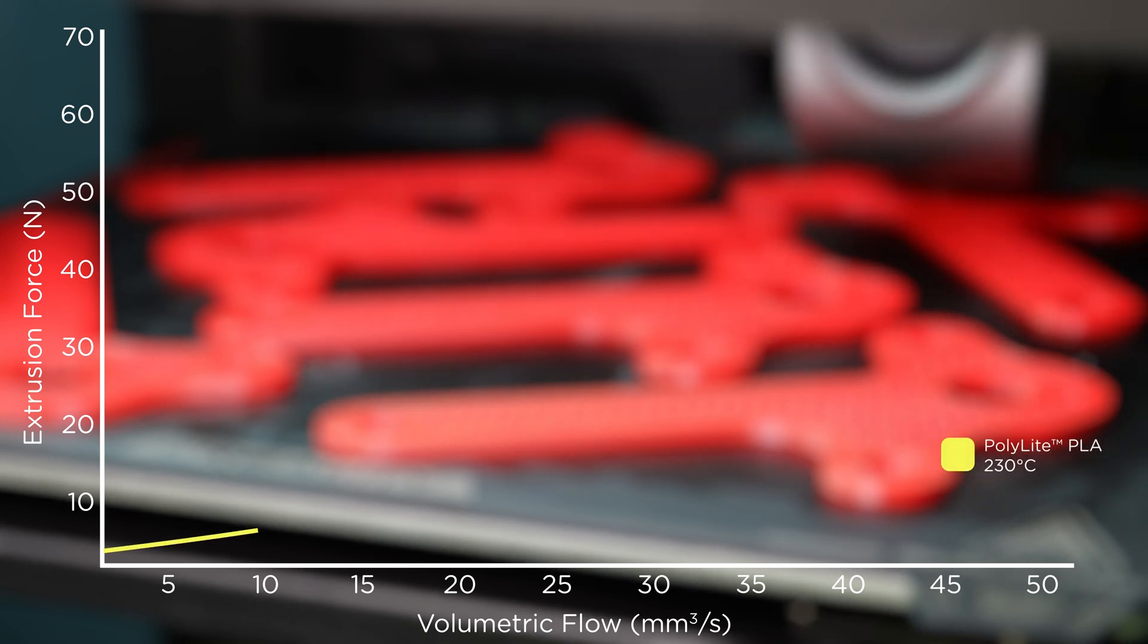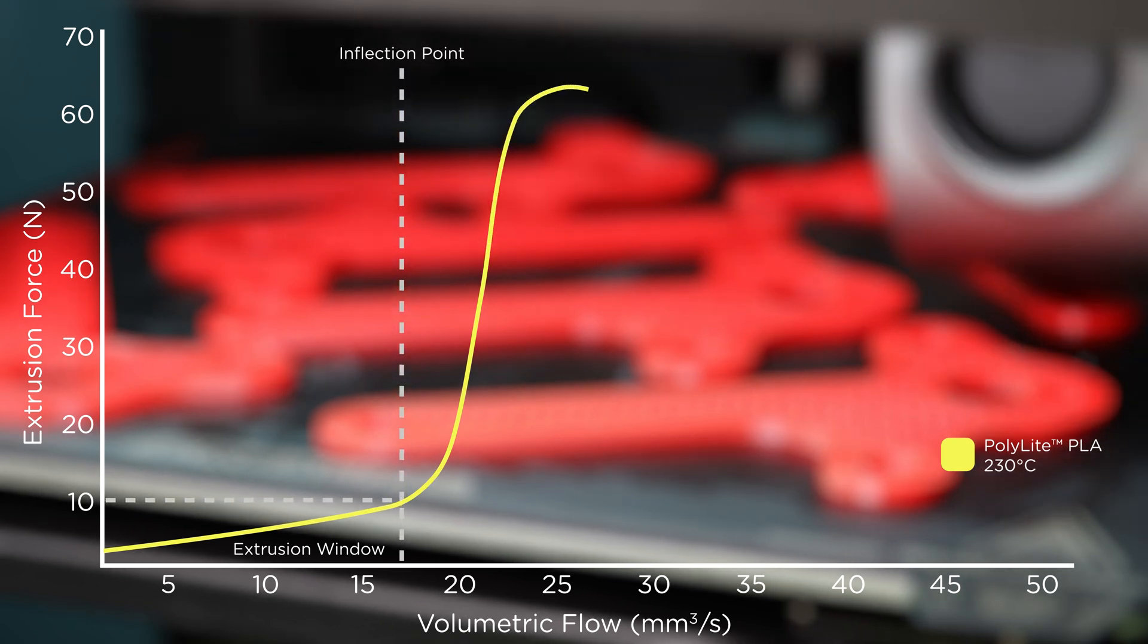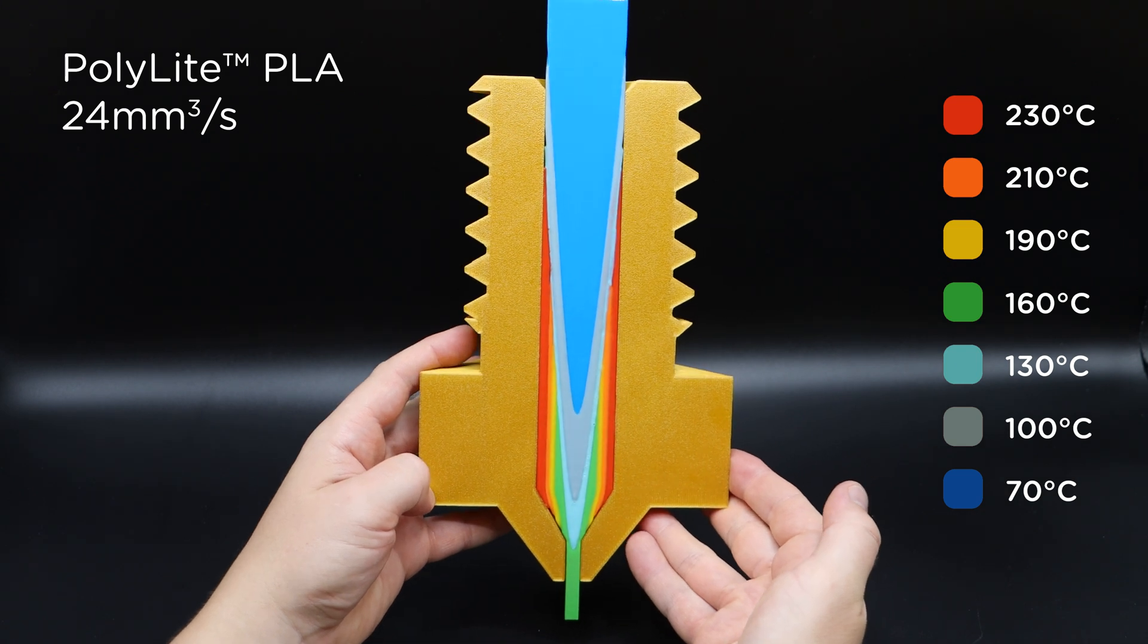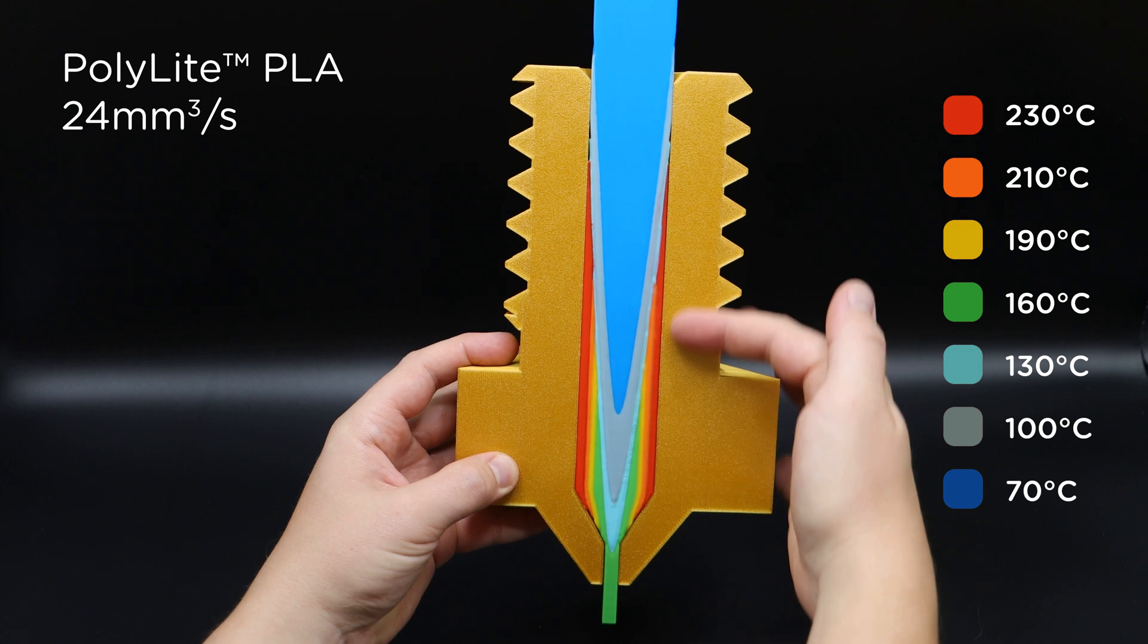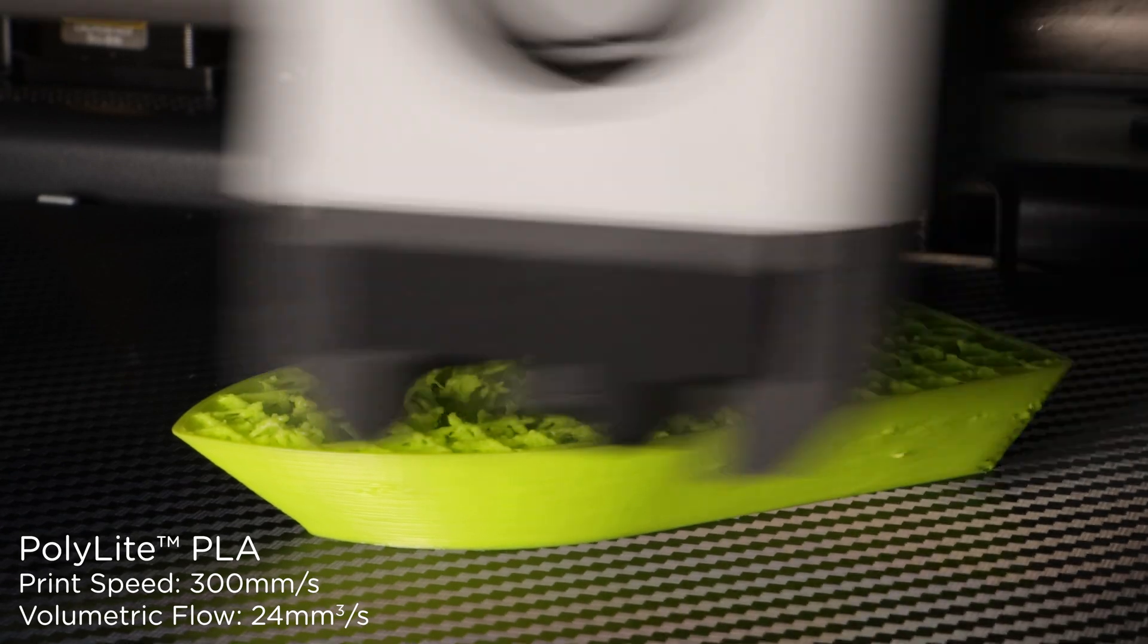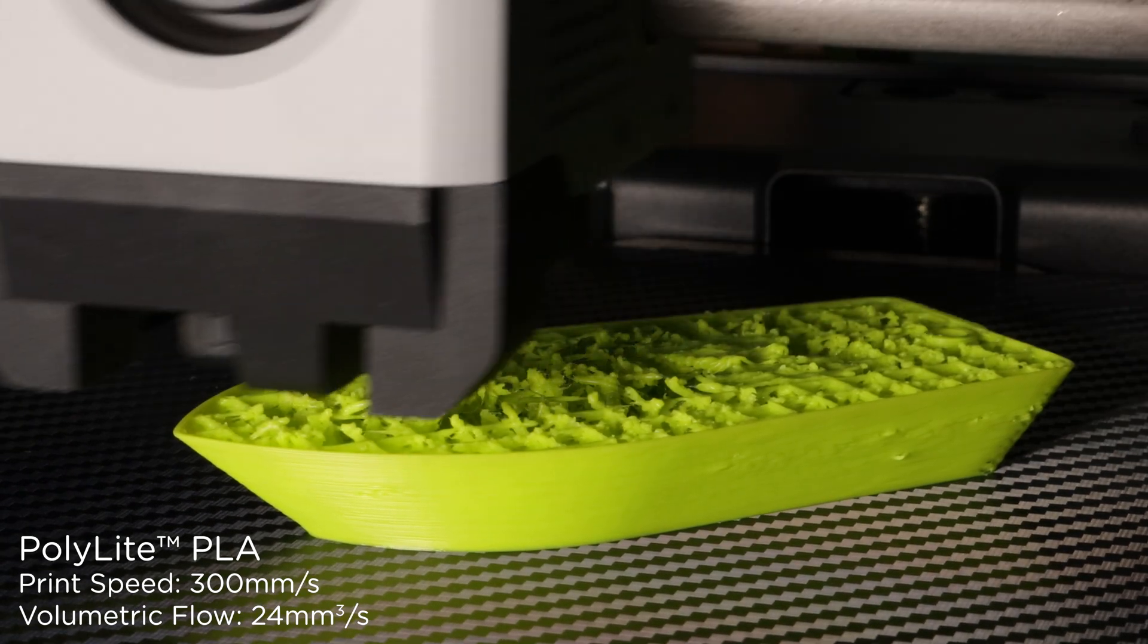If we look at this graph from the ECP, showing our regular PolyLite PLA extruding at 230 degrees, there's an inflection point where the extrusion force rises exponentially. This is caused when the filament doesn't reach its molten state inside the nozzle, and the shearing forces start fighting back against the hemera. The result of this is under-extrusion, poor surface quality, weak layer adhesion, and eventually a failed print.